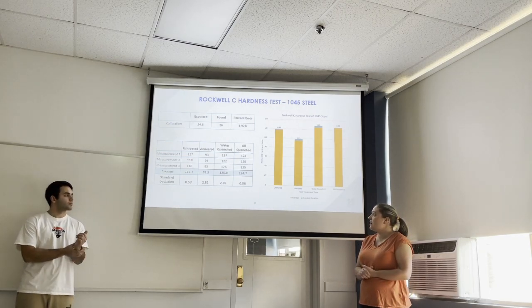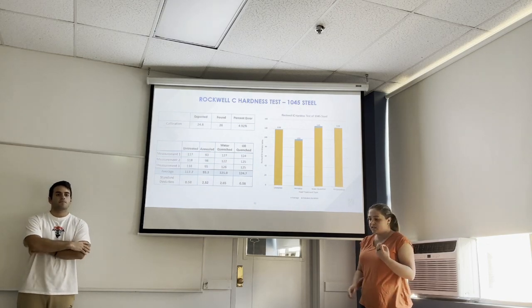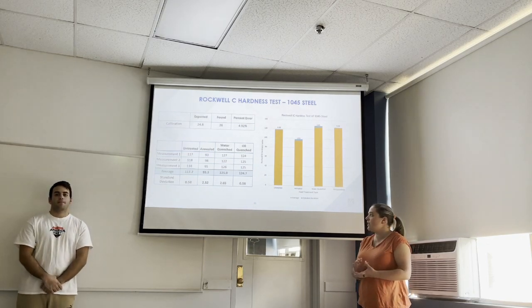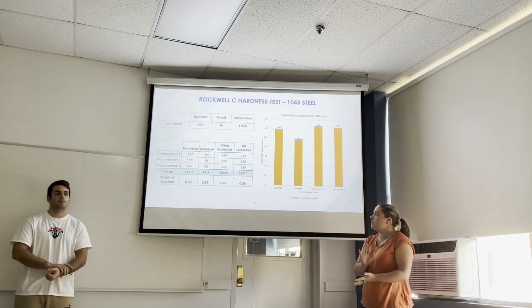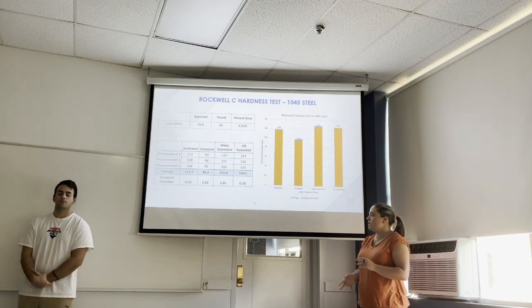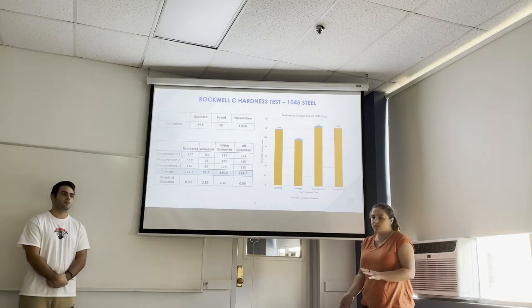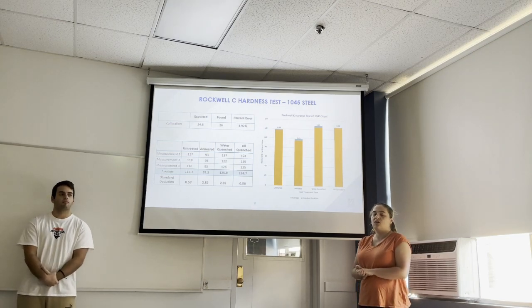One thing to note that Nick will talk about a little bit later is that our oil quenched averages between Rockwell B and Rockwell C did not correspond in the way that we expected. For this though, all of the other numbers did. So we have untreated, annealed, and water quenched that appear to have the same relative hardness. We even have water quenched having the same higher amount of standard deviation than all of the other heat treatments.